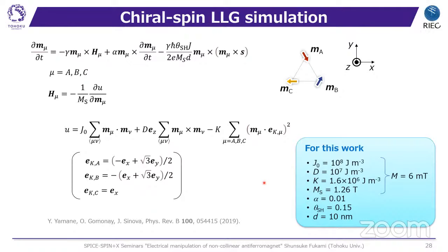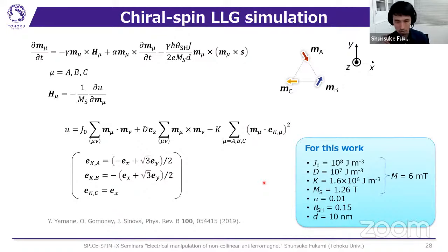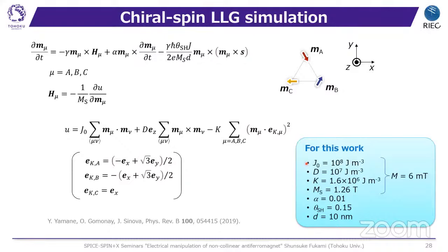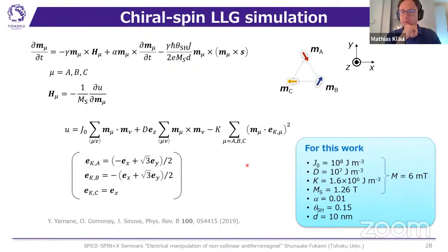And also whether applying mechanical strain would assist in the switching, or would it not help? I don't know, but the switching current depends on the material parameters. So if you can change the material parameters in better directions, the threshold current should decrease. Okay, thank you. So in particular, if the anisotropy goes down, then I guess the threshold goes down. Yes, I think so.